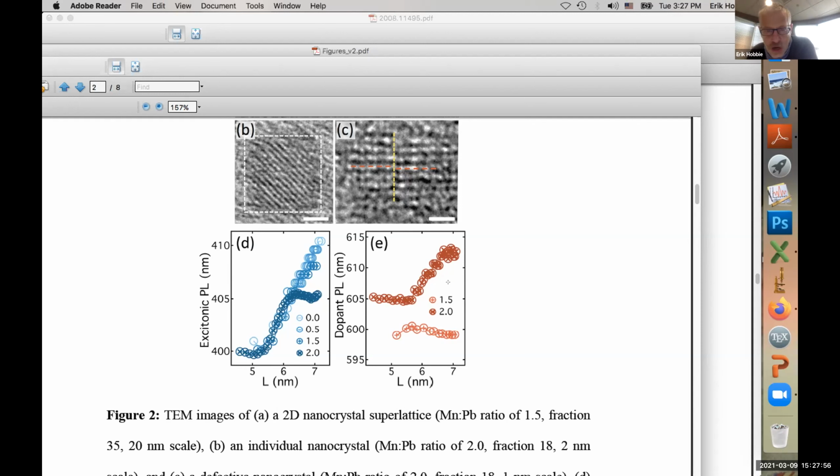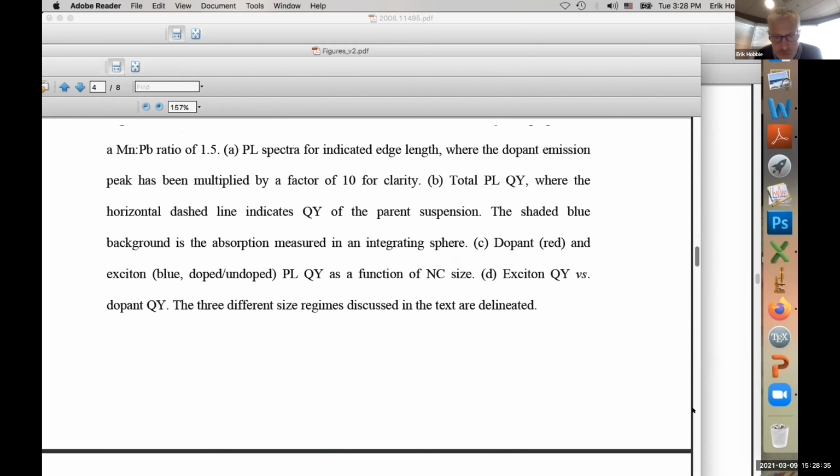So the question becomes, how does adding more dopant cause a redshift? How do dopant interactions shift this red emission? Without detailed analysis and study, I will answer in the spirit of the previous crazy idea. So you're telling me increasing concentration of dopants induces redshift. Yeah, it makes a redshift in the dopant emission, and it causes a drop in the dopant quantum yield. So there must be something going on, and you can see that actually in the non-radiative rate. It's a really nice set of data that we got. I just don't understand it yet.